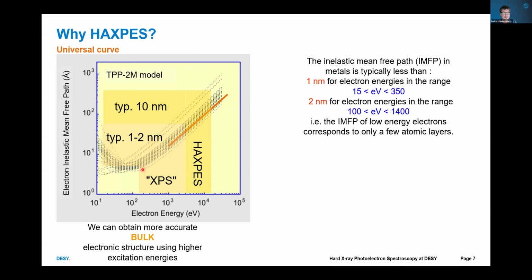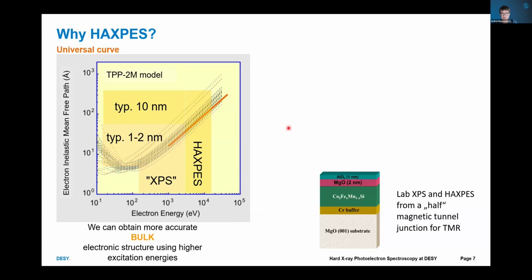And you see that in the VUV range, the electrons travel about 1 nanometer without scattering events. In the soft X-ray range, it's about 2 nanometers. This means that soft X-ray spectroscopies are very good for surface science. But if you want to study bulk electron properties, you have to go to hard X-rays.